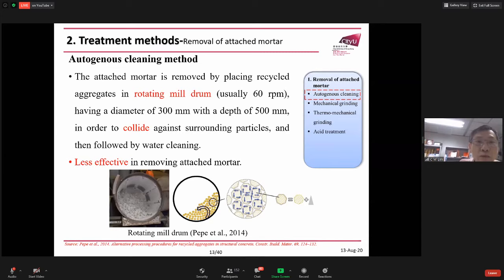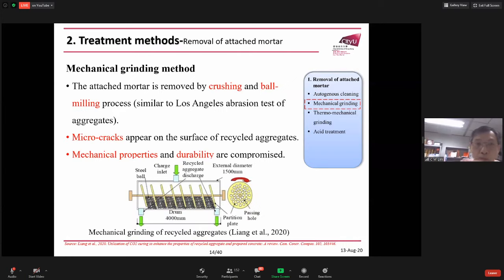The attached mortar is removed by placing recycled aggregate in a rotating mill, which has a diameter of 300 millimeters and a depth of about 500 millimeters. It collides against surrounding particles, followed by water cleaning. This method is less effective in removing the attached mortar. The next method is the mechanical grinding method. The attached mortar is removed by crushing and ball milling process, which is similar to the Los Angeles abrasion test of aggregates. Micro cracks appear on the surface of recycled aggregates, and the mechanical properties and durability are compromised. So this method also has some limitations.